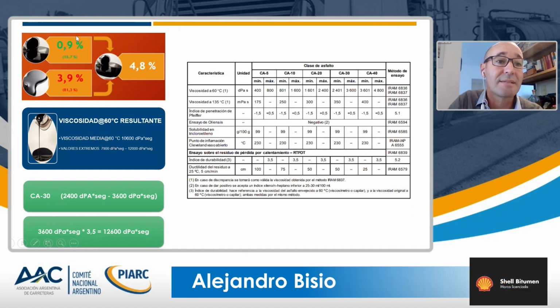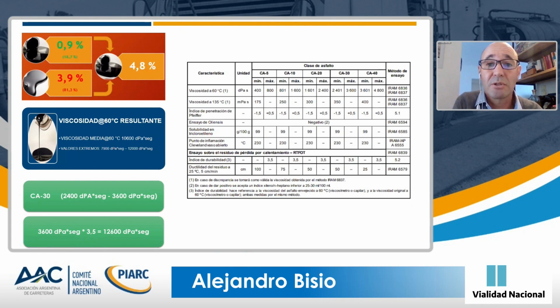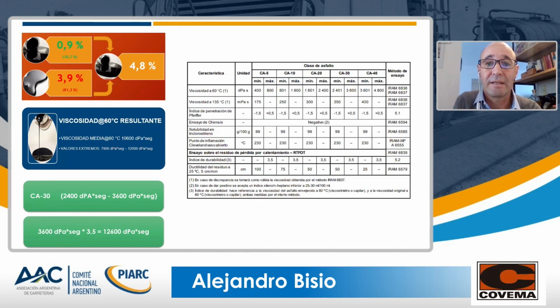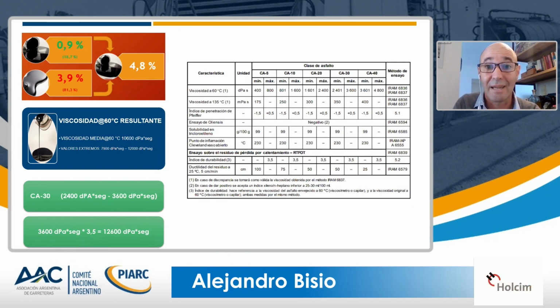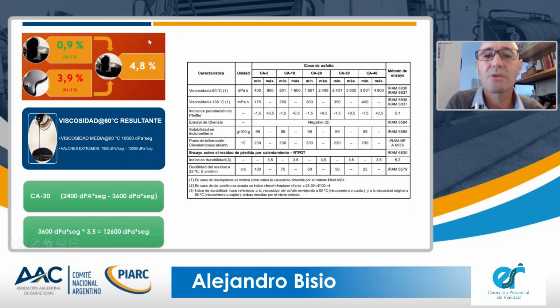As to the asphalt mixture, 0.9% came from the RIP, and 3.9% came from the virgin asphalt binder. From the percentage point of view, if we focus only on the asphalt binder system, 19% was the asphalt coming from RIP and 81% from the virgin asphalt. Mean viscosity at 60 degrees was 10,600 decipascals per second. In order to have this viscosity in the resulting asphalt binder, it was not necessary to use a lower grade asphalt binder. We just used a CA30 as the virgin binder.